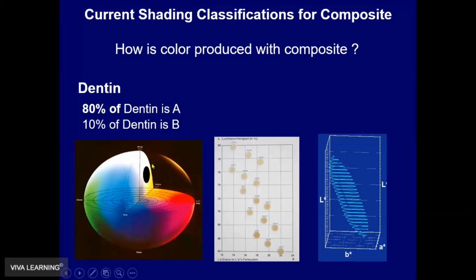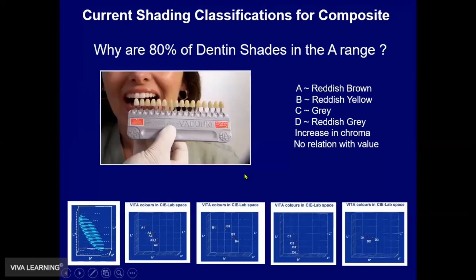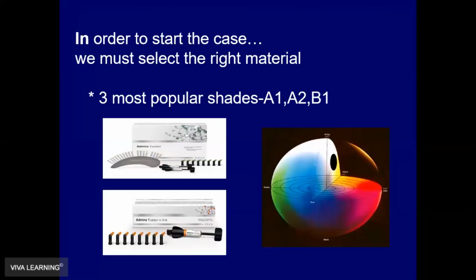But what we do know in the human color range, 80% of the dentin is in the A range, 10% in the B range. This is the human colors up here, and this is the A range right in here. It fits very nicely. So we want to leverage the 80%: the dentin shades you use should be in the A and B range. C's and D's really don't exist. These are different A and B dentin shades with different chroma enamels on top of them to influence that. They are manufactured shades. So we want to leverage our dentin shades into the A range and possibly the B's.